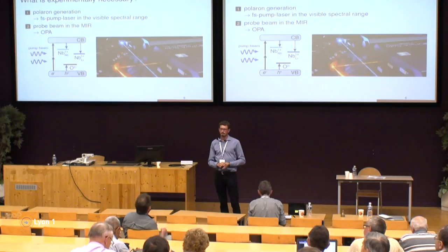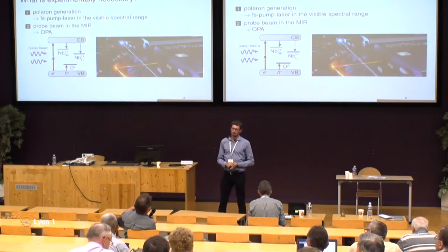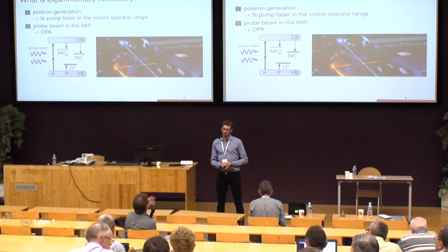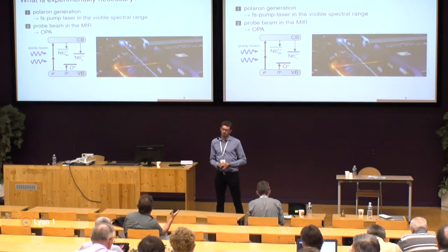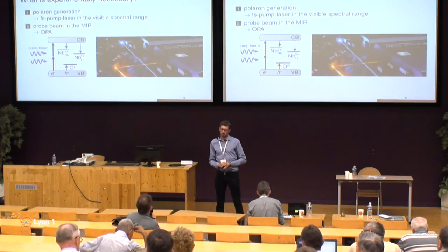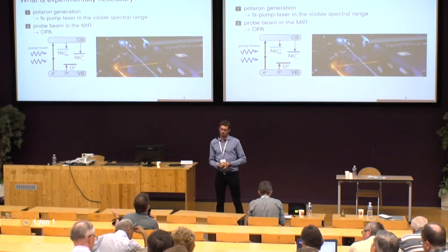Another question? Since you're using the hydrogen as a probe, essentially, to what extent can your result then be generalized to the small polaron, versus a more specific distortion of a small polaron by a bond that is existing close to where the hydrogen is? Since you measure the shift, the shift determines the environment of the hydrogen or the OH, essentially. And so how much is it really true to generalize that distortion that you see to a polaron that does not involve the hydrogen?